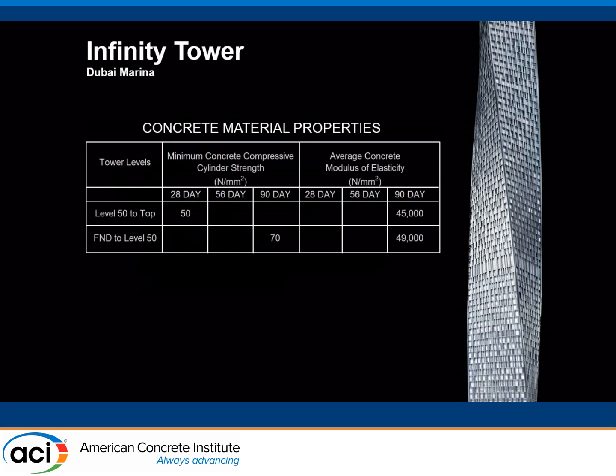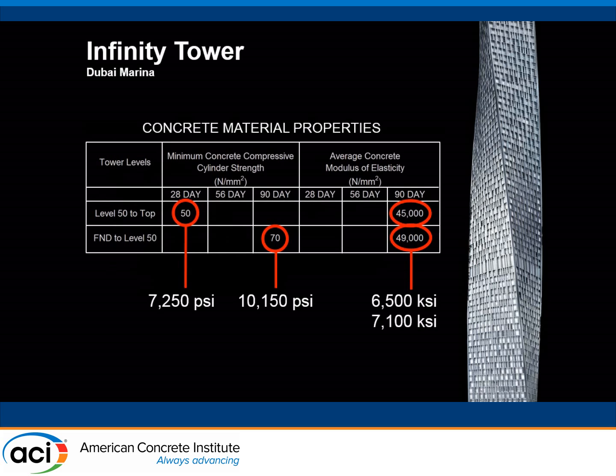Some of the concrete material properties, I'll skip right to the imperial units for the metrically challenged here. From the foundation to about level 50, we had about 10,000 PSI concrete. Not totally exotic, but certainly for Dubai. You can't do in Dubai what you can do in the U.S. all the time. So this is certainly a little bit of pushing the envelope, at least at the time, for what could be done in Dubai. And then we tailed it off to about 7,000 PSI concrete in the upper third of the building. And we did specify modulus of elasticity at 90 days, which was quite challenging actually for the ready-mix guys to achieve. We had a lot of back and forth on that one. I'll talk about that in a little bit as well.